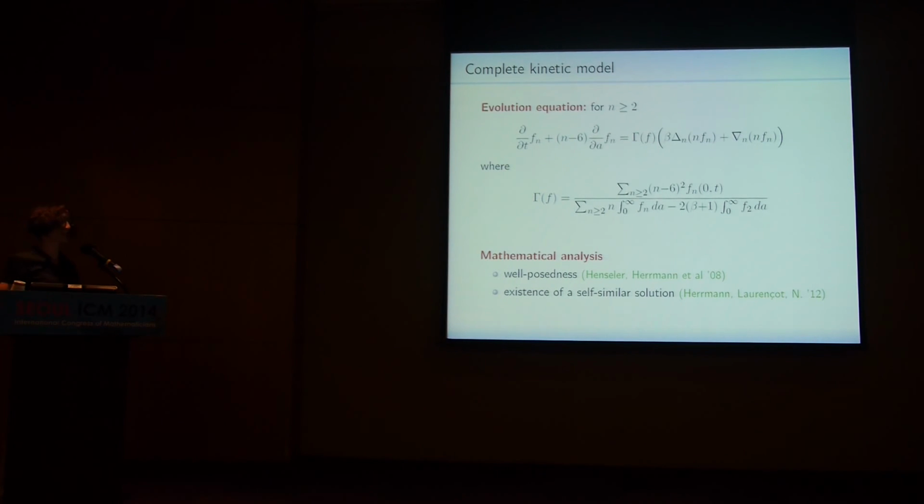So we couldn't say anything about uniqueness of the self-similar solution, nor anything about the long-time behavior in general given any initial data. And again, the question is, okay, there is a self-similar solution, and here's a transport term. Transport always remembers the details of the initial data. Here's something like a diffusion, but discrete, and it's also in the n variable. Is this enough to drive the system to a universal long-time state?